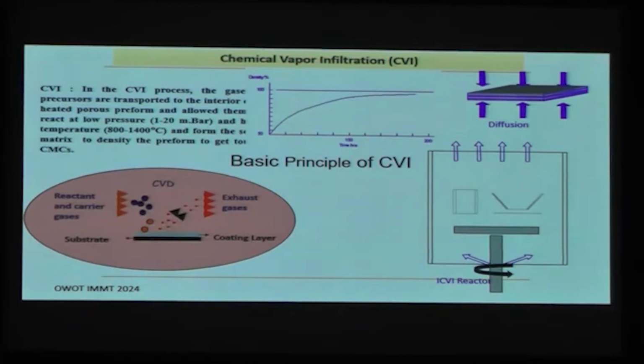So CVI is a chemical vapor infiltration process where we bring the gaseous reactants and allow them to infiltrate the heated porous preform and react at high temperature and low pressure, and it forms a refractory solid. And if you keep on doing this, the whole preform, which is porous, will be converted into a tough composite. Basically here, this is the preform where the gaseous reactants are infiltrated via chemical diffusion, and the reaction is taking place.